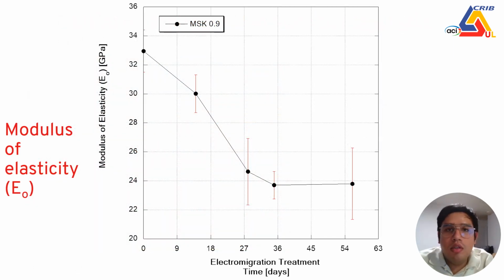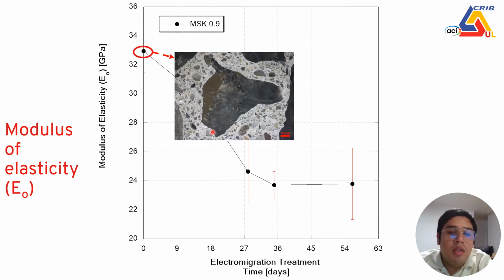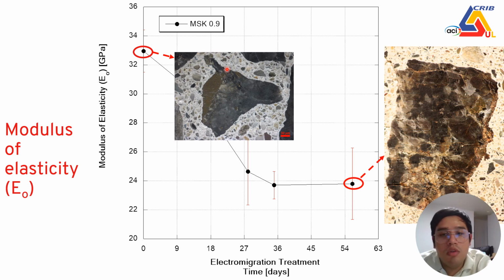After performing all the testing mentioned before, we found that the modulus of elasticity was the measurement that can show us the evolution of the detrimental reaction of the sulfide-bearing aggregate. You can see here in the graph, at 28 days of curing, the performance of the concrete and how it decreased as we apply more electrochemical treatment with time: 14 days, 28 days, 35 days, and 56 days. And you can see here in the picture that at 28 days of curing, the iron sulfide minerals were not touched, were not affected. But once the chloride reaches the surface of these iron sulfide minerals, we can see here how they can be affected by this reaction.